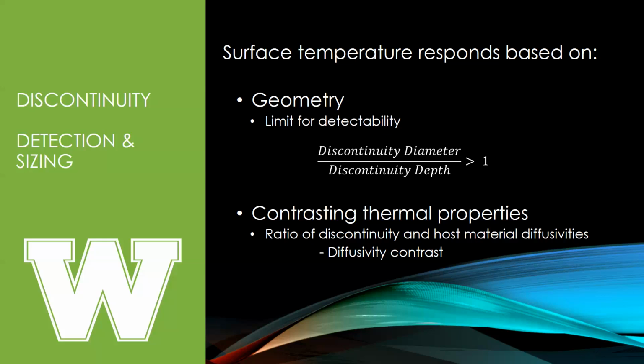So what I mean by that is if we draw two objects here, and we're going to be imaging these from the top. In object 1 on top here, we have a discontinuity that's very narrow, like this. In object 2, we have, say, a delamination that's very wide. If we're looking at this object on top from above, it's going to be very, very hard to see this discontinuity because all we're going to pick up is this very, very tiny end here compared to the depth of it. So in this top one here, the diameter, let's say it's 1. If we say its depth is 3, 1 over 3 is less than 1, it's going to be really hard to pick that discontinuity up.